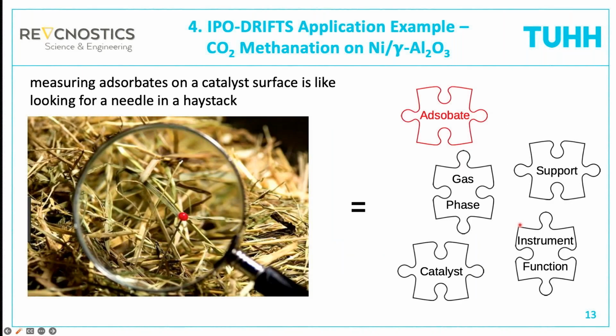And now we would like to measure the adsorbates on the surface of the catalyst. And this is a little bit like looking for the needle in the haystack. So we have, of course, an IR absorption by the adsorbates, but there are many more things in the system that absorb the IR light. This is, for example, the gas phase over the catalyst, which is a very strong disturbance. Then we have also IR absorption by the catalyst support, so by the bulk material, and also by the bulk catalyst itself.